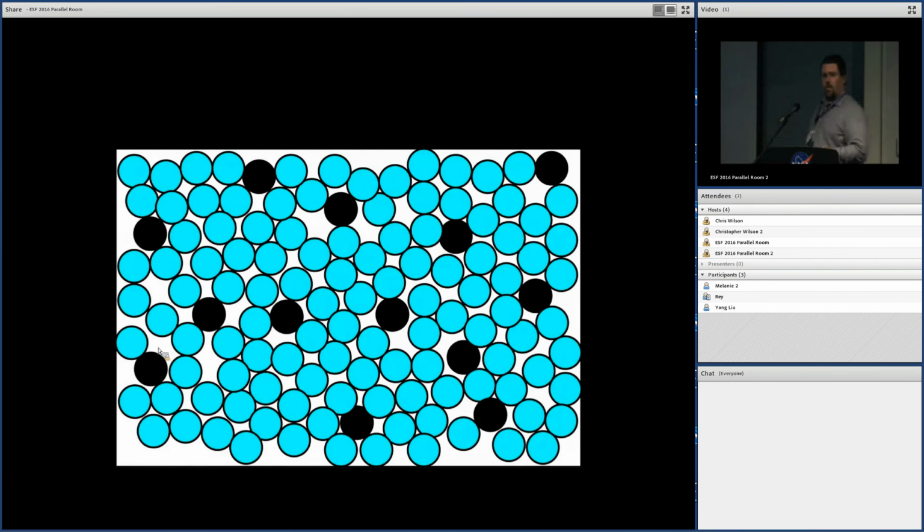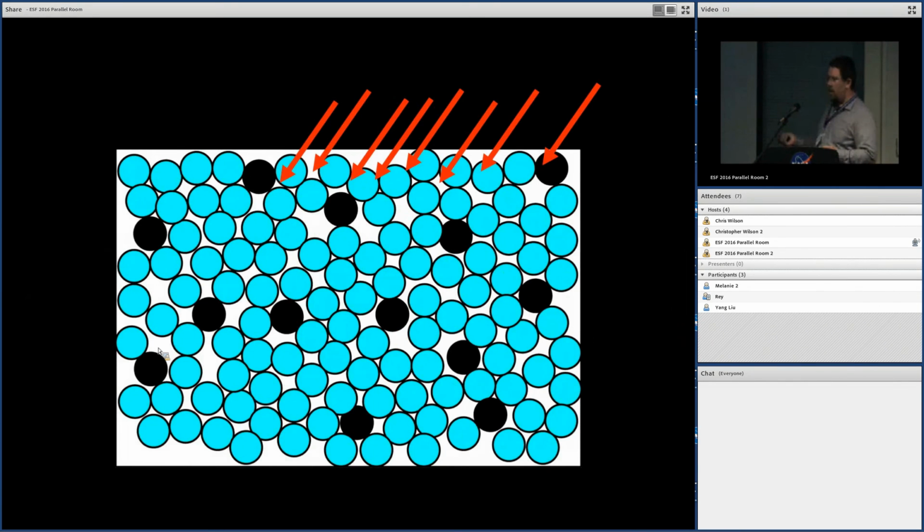If you replace that strongly absorbing matrix with a transparent matrix like halide, all of a sudden when you shine your light on it, you get a bunch of scattering down and into your sample. This multiple scattering allows you to interact with many more particles, and for certain light paths, it decreases the probability of a given ray path making it back out of the sample.